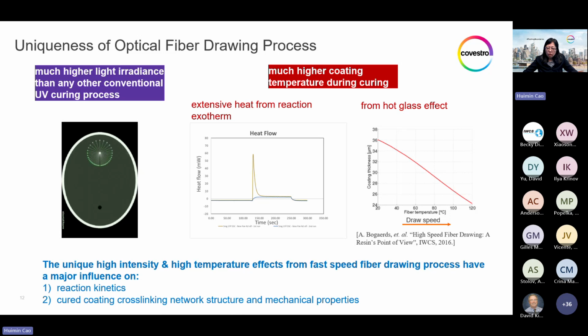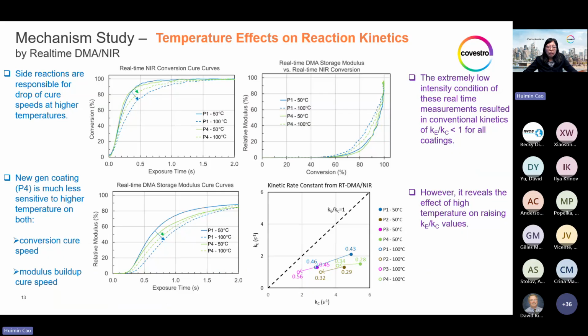And so from a photopolymerization process point of view, both intensity and temperature will have major influence, first on the reaction kinetics, second also on the cross-linking network structure, and subsequently coating mechanical properties. For the effect on kinetics, we used a custom-made instrument coupling together a real-time NIR with a real-time DMA, so that we can monitor simultaneously conversion and modulus in real time at the set temperature.